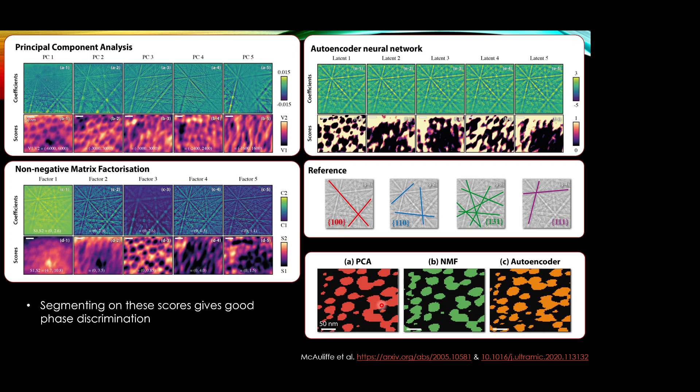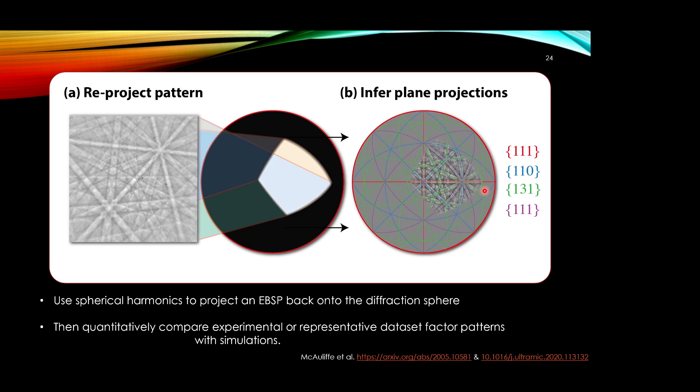But if we take and we know that there are specific crystal planes, what we can do is imagine extracting the particular bands out from the diffraction pattern and do band profile analysis on those particular crystal planes. Very fortunately, we've done collaboration with Ralf Hielscher and colleagues to create the spherical radon transform, and we can do band extraction from that mathematics. That enables us to directly extract the band profiles from the spherical projections. This is the sum across the entire band summed across all of the families that are present. We can now sum and look at the differences between the gamma and gamma prime ascribed experimental patterns and the simulated cobalt nickel and cobalt three aluminum tungsten. That's similarly our gamma gamma prime.